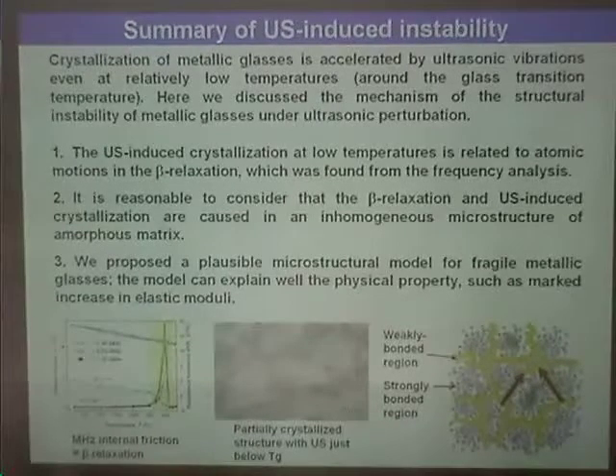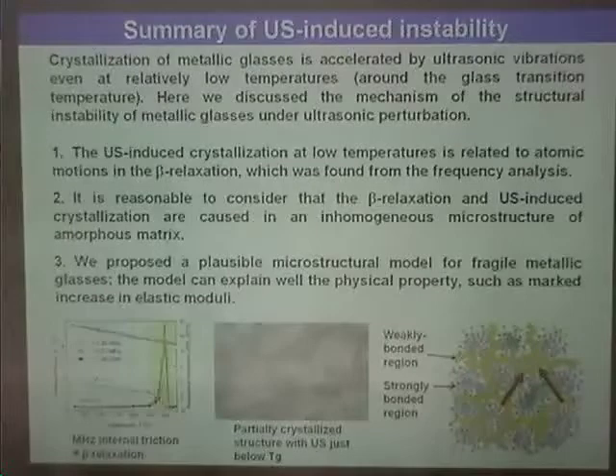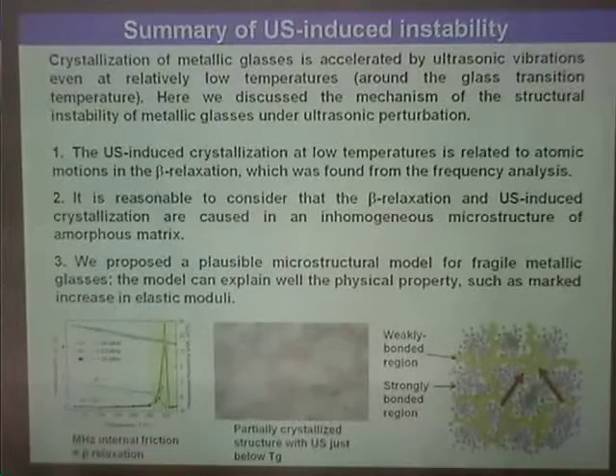Yeah, part of the issue here, especially from the simulation standpoint, is that to measure any of these quantities like elastic moduli or densities, you have to have some averaging length. So when you put up a picture like small local hard regions embedded in soft regions, do we have enough hard region that we could actually define that region and give it a continuum property? It's not clear that those regions are large enough to think of them in any way as continuum regions.